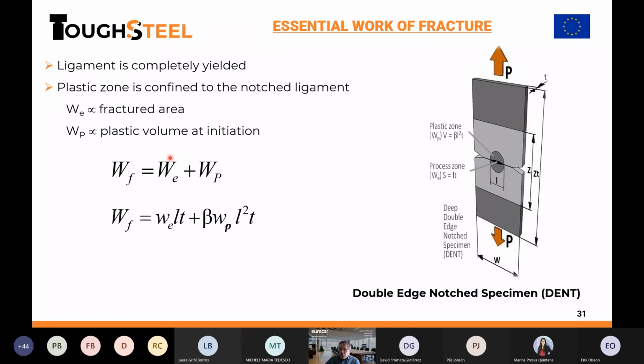Because this is related to area, the fracture value is proportional to area. Here is the area. We can define a new parameter that is material dependent, not area dependent. This is the ligament length times the thickness, so this is the cross section of the specimen subjected to tension. And the same for the plastic work, but now because plastic work is proportional to volume, we have to include here the volume of the specimen corrected by a factor.